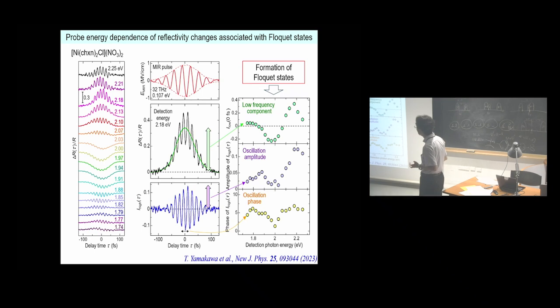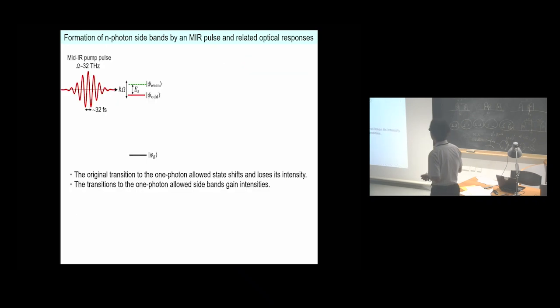This figure shows the reflectivity changes for various probe energies. From this data, we can extract the spectra of the low frequency component, oscillation amplitude, and oscillation phases, as shown here. These spectra should reflect the formation of Floquet states. Here, I will explain the result qualitatively.